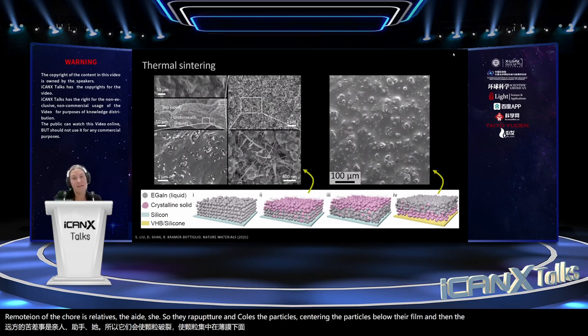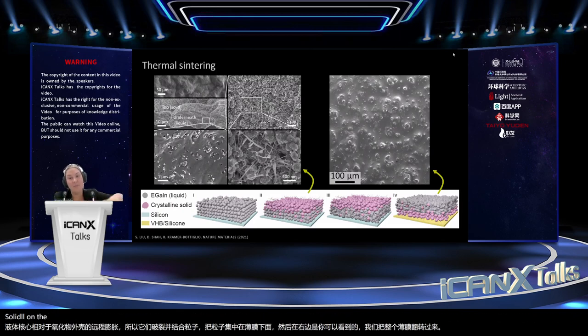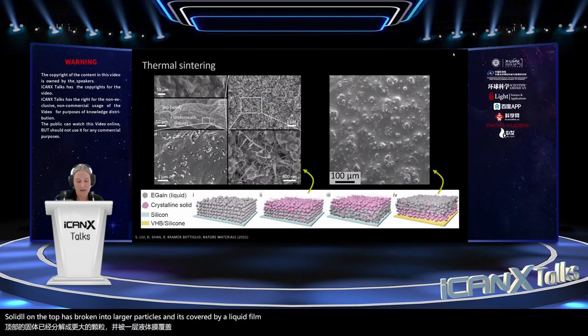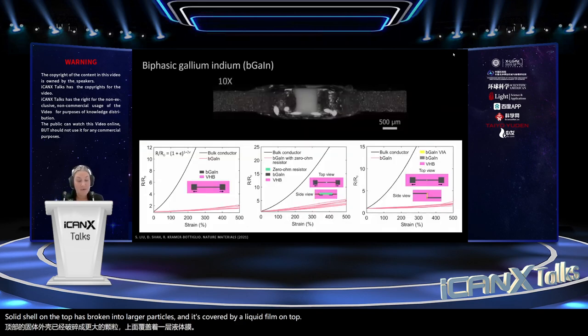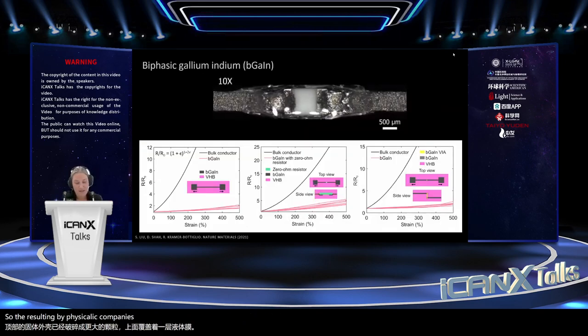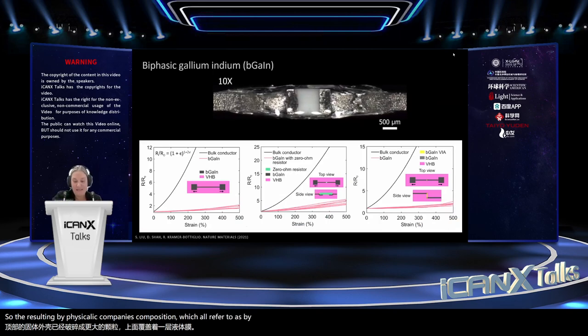And then on the right is what you can see. We just flipped over the entire film so that the solid shell on the top has broken into larger particles and it's covered by a liquid film on top. So the resulting biphasic composition, which I'll refer to as biphasic gallium indium or BGaIn, has this very unique strain insensitive behavior.